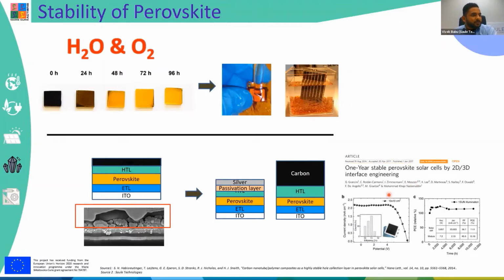And there is a work from Giulia Grancini in the year 2017, where she made a perovskite module implementing both strategies, where she used 2D material, like I was mentioning in the first slide, the advantage of 2D for stability, as well as a carbon electrode, and she got stability over 1 year, more than 10,000 hours. And lately a lot of articles are also being published reporting stability of more than 1 year, which is quite interesting, with studies where scientists are working on different passivation, and also different crystallization and grain growth of perovskites.